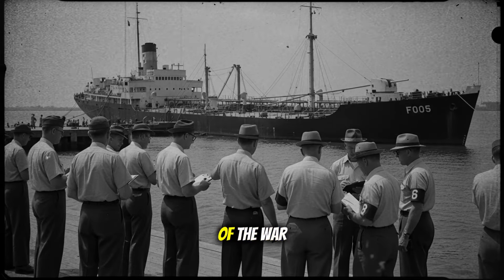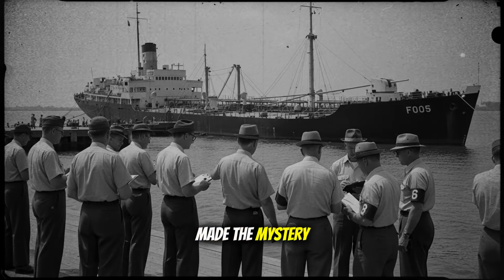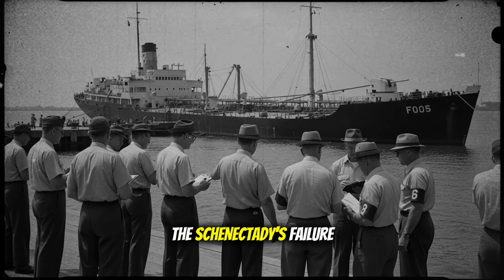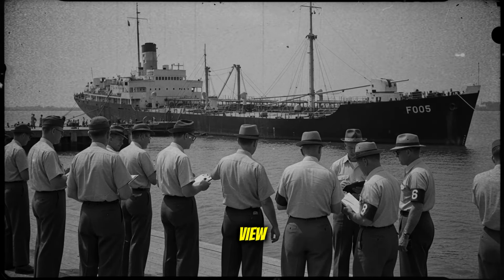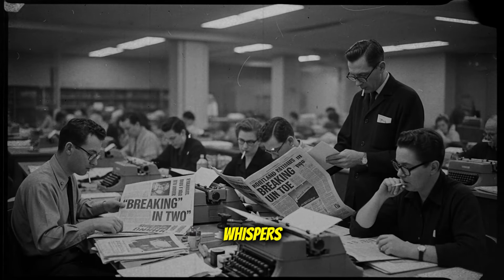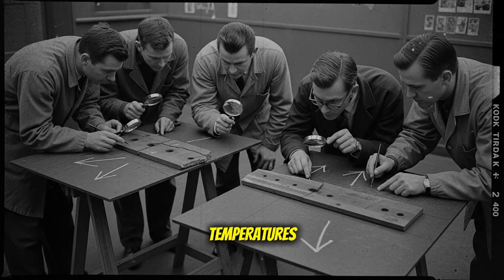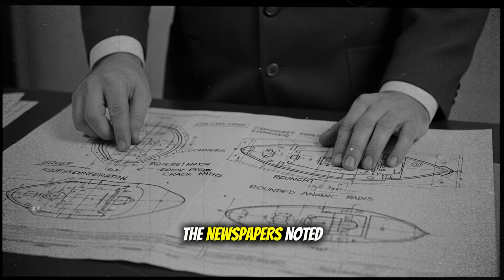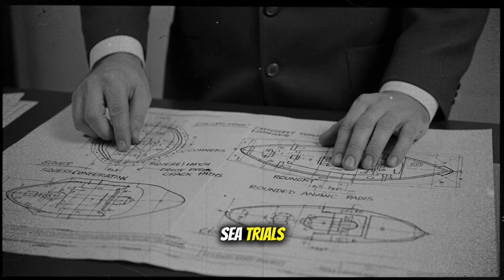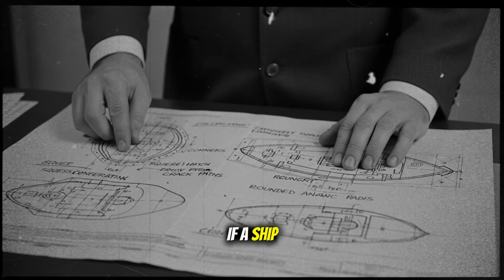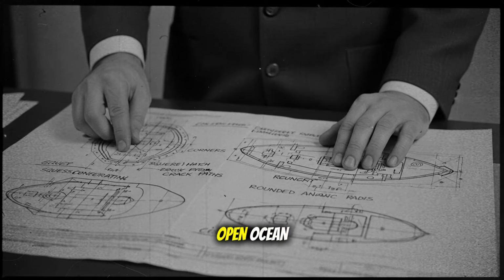It was not the first crack of the war-built fleet, but it was the moment that made the mystery impossible to ignore, because the Schenectady's failure happened in a safe harbor and in full view, lending shock and urgency to earlier whispers about welded ships splitting unexpectedly in cold conditions. The anxiety had been growing as winter spread down from the North Pacific and across the North Atlantic, places where water temperatures pressed steel toward its hidden limits and turned minor flaws into fatal lines racing through a hull. The Schenectady's break, the newspapers noted, came in calm weather just after sea trials, which only deepened the dread. If a ship could break here, what awaited her sisters on the open ocean?